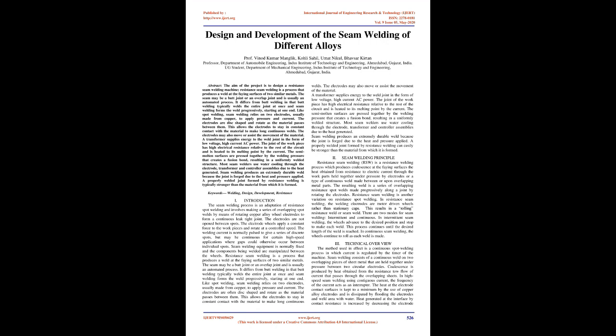A transformer supplies energy to the weld joint in the form of low voltage, high current AC power. The joint of the workpiece has high electrical resistance relative to the rest of the circuit and is heated to its melting point by the current. The semi-molten surfaces are pressed together by the welding pressure that creates a fusion bond, resulting in a uniformly welded structure. Most seam welders use water cooling through the electrode, transformer, and controller assemblies due to the heat generated. Seam welding produces an extremely durable weld because the joint is forged due to the heat and pressure applied. A properly welded joint formed by resistance welding can easily be stronger than the material from which it is formed.